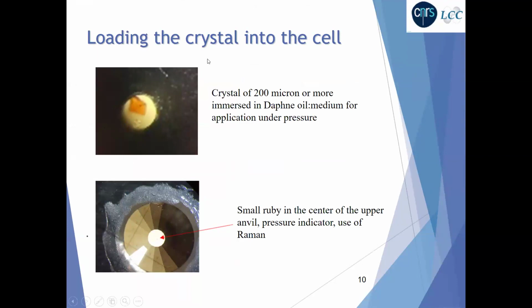Concerning the loading of the crystal into the cell, as you can see on this picture, we have our little crystal. The size of the crystal should be around 200 micron, not too big, of course, but not too small as well, because it's easy to lose your crystal. Loading the cell is quite the trickiest part of this job. It can be very difficult.